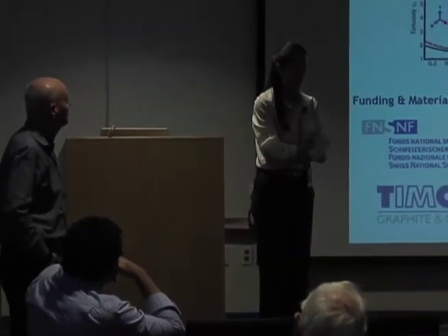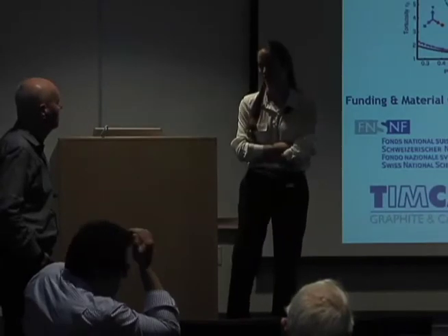Yeah, I guess there, the question is often how much. So carbon nanotubes are really attractive for capacitors because it's often a surface storage of lithium. I think certainly there's a lot of interest in aligning materials. So maybe some of the techniques that are known for vertical alignment and orientation of nanotubes could potentially be leveraged for graphite. But graphite is probably more of an interesting material for batteries, whereas for capacitors, carbon nanotubes are potentially more relevant.